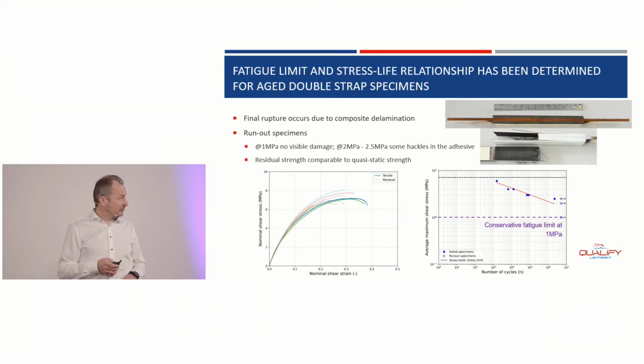It must be said that at the specimen at 1 megapascal, we could not even see any damage at the adhesive. For the specimens tested at 2 megapascal, 2.5, we could see minor small hackles, small cracks in the adhesive, but without any significant influence on the mechanical behavior. So there are quite a lot of repeat tests, so this is repeatable behavior. Final rupture of the specimens was always introduced as failure at the composite plates themselves near the interface with the adhesive, so interfacial damage or delamination.